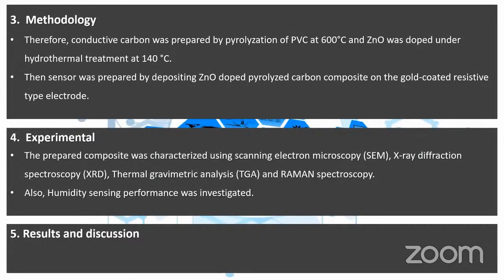Methodology. In this research, we use waste PVC and dope it with zinc oxide. We pyrolyze the PVC in an argon environment to 600 Celsius, and hydrothermal treatment was done to prepare zinc oxide nanoparticles on the surface of the PVC polymer.